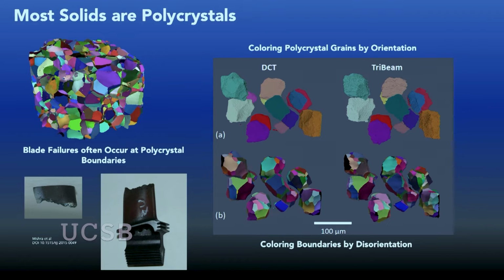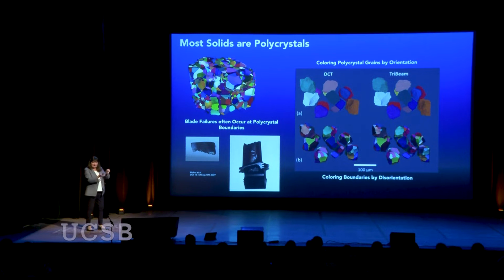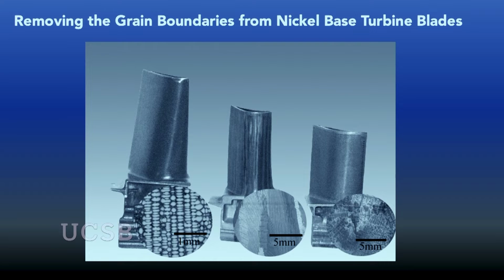And so here's an example of a turbine blade. So that would slide into that disc and rotate to generate thrust. And this failure has basically occurred by damage that develops in between these little grains that eventually joins together and causes this failure. And so, as engineers, what might you do about that? Well, this was an interesting question. Some years back, there was an engineer at GE that said, well, if the materials are failing at the boundaries, why don't we just take them all out? Let's make them single crystals, just one crystal for the whole blade.